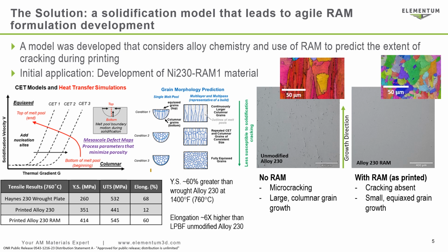The cracked printed alloy 230 without RAM actually has higher yield strengths at temperature than the wrought plate. But you can see that the elongation and the ultimate tensile strength are drastically reduced because of the cracking that has caused brittleness. With RAM, we have high yield strength, and we maintain the high ultimate tensile strength, and since the cracking is absent, we have even recovered most of the elongation capacity of the alloy. So it's clear that the RAM process completely changes the behavior of this material when printed, and modeling helped quickly identify the combination of RAM composition, the concentration, and the particle size ranges to test.